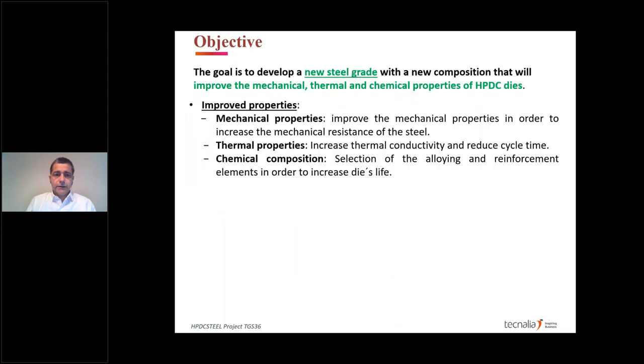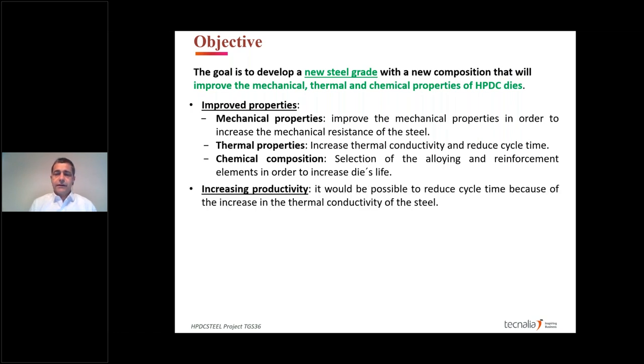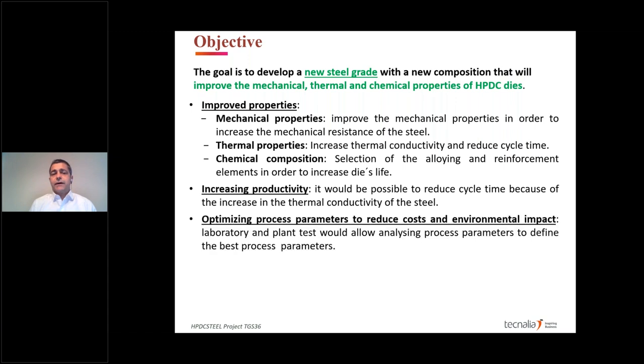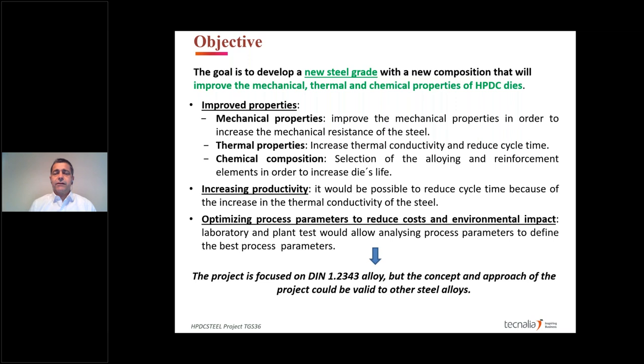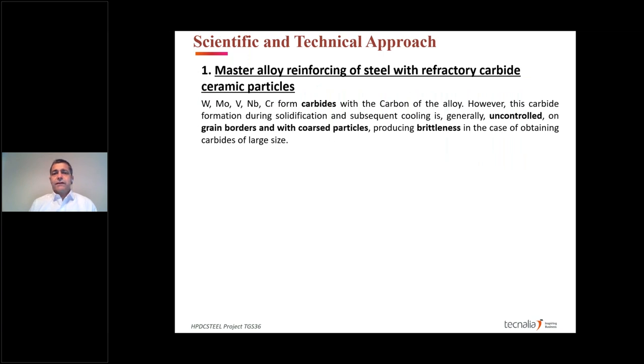So if we go ahead, we can see the goal. The goal is to develop a new steel grade with improved mechanical, thermal, and chemical properties, with the scope of increasing productivity and optimizing the process parameters, but the most important one, to increase the life of the steel. Current dies suffer from thermal stresses and they have a limited life because of the high pressures, temperatures, and the chemical attack of the aluminium or the magnesium over the die.